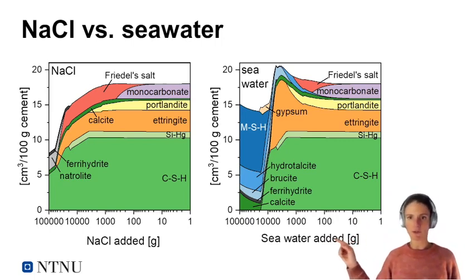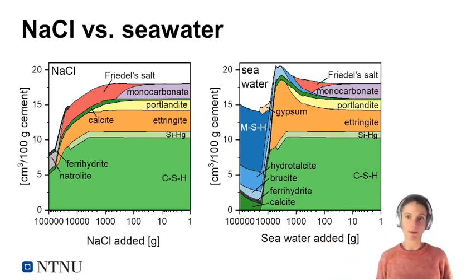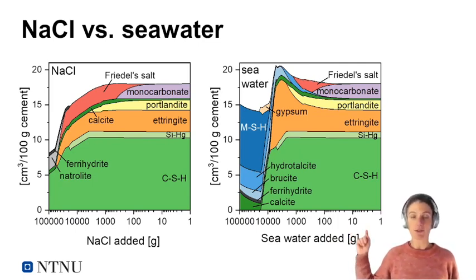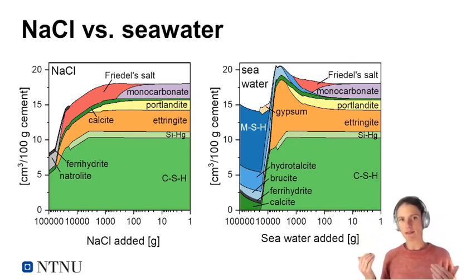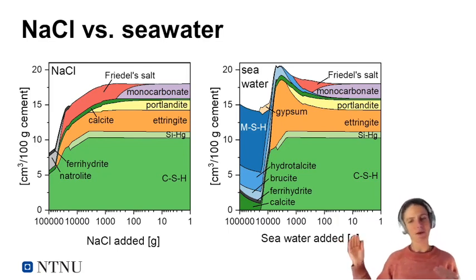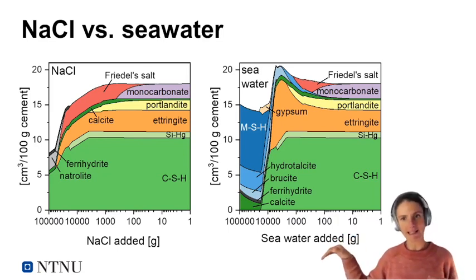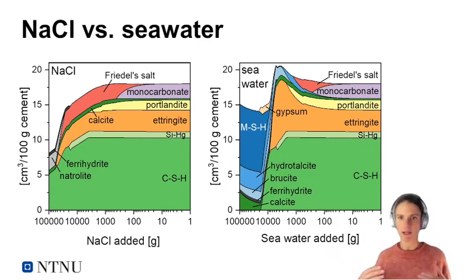And what we're doing when we move in towards the origin is we're adding more and more sodium chloride solution. What we can see that's changing in the case of sodium chloride solution is, on the top, we have the monocarbonate, the purple phase, that's going over into the red phase, which is Friedel's salt. So we're binding chlorides in Friedel's salt. And the other thing we can see, because I'm not going into detail in all the phases, is a general decline in the total volume of the phases formed. So when we're adding more and more sodium chloride, we are in a way leaching out solids after a while.